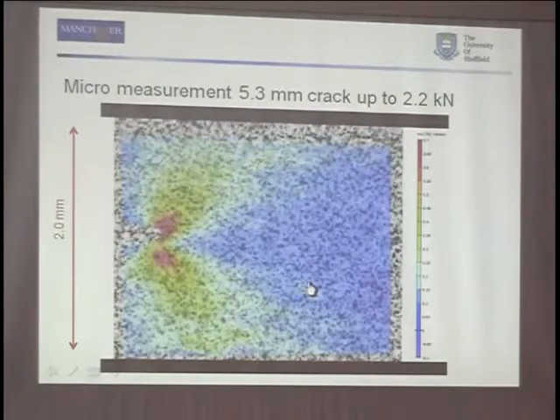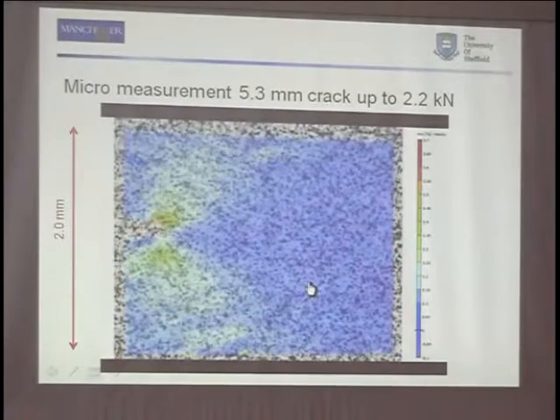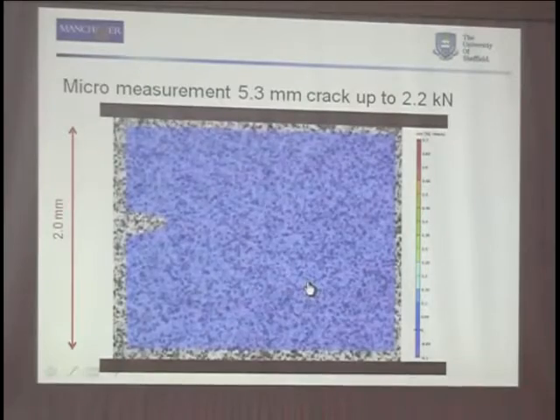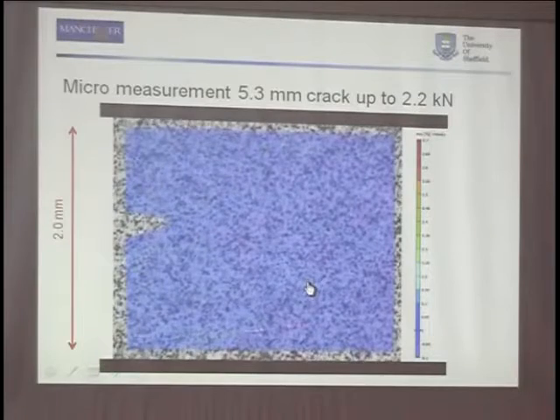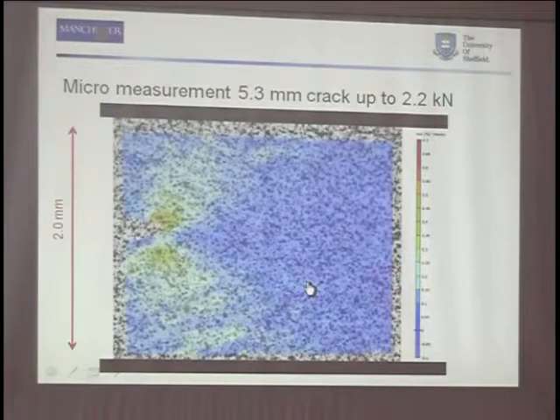So you can see that crack there, it's not straight, that's the fatigue crack, that's about 5.3mm. Probably play that again. And the field of view is about 2 millimeters by 2.5 millimeters. In some tests we've got some data behind the crack tip, but we're not showing that here today. But the data is available if anybody wants it.